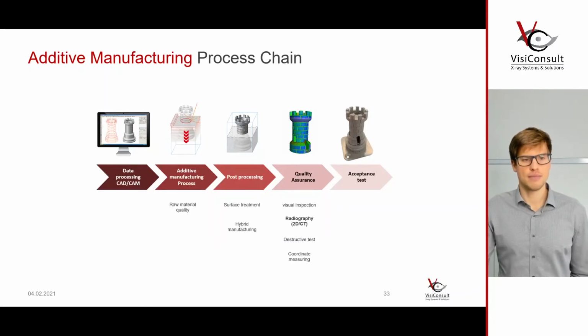So let's look at the additive manufacturing process chain. Where are we? So data processing is the first step that happens. So somebody creates the part. It's typically design engineers. Then the additive manufacturing engineers are transforming these raw data into layered data, because this is what the additive manufacturing machine needs to build layer after layer in an additive way. And once it's built, you will have some kind of post-processing. You need to remove the support structures. You need to do maybe some surface treatment, maybe some heat treatment. You need to get rid of residual powder.